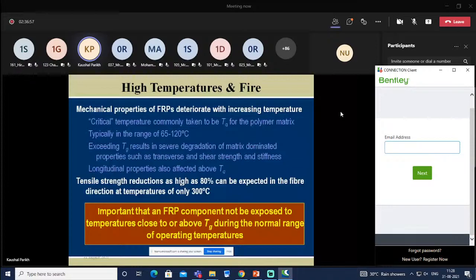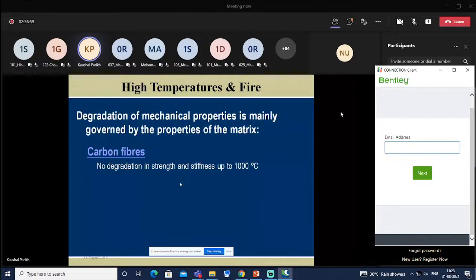Now, the degradation of mechanical properties is mainly governed by the properties of the matrix. If we say the carbon FRP is concerned, there will be no degradation in strength and stiffness up to 1000 degrees centigrade, as visualized by various researchers. But as far as glass fibers are concerned, a 20 to 60% reduction in strength will be reached at 600 degrees centigrade for the glass fiber. Repeat, right now, this is only as far as the individual fibers are concerned.